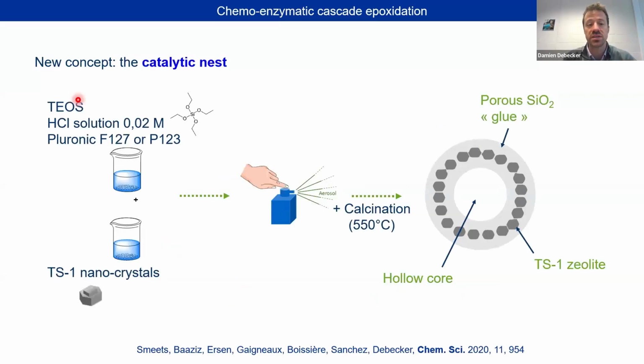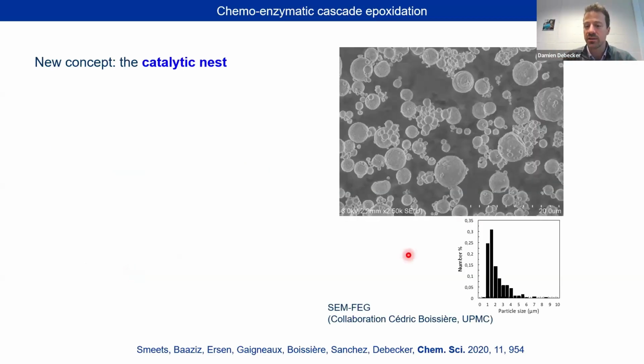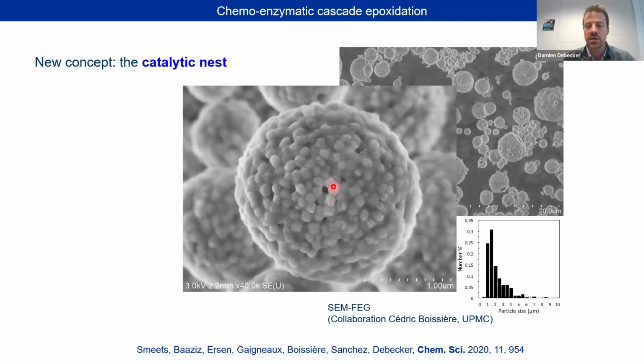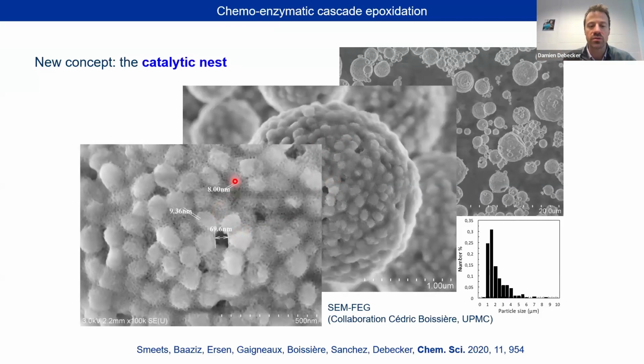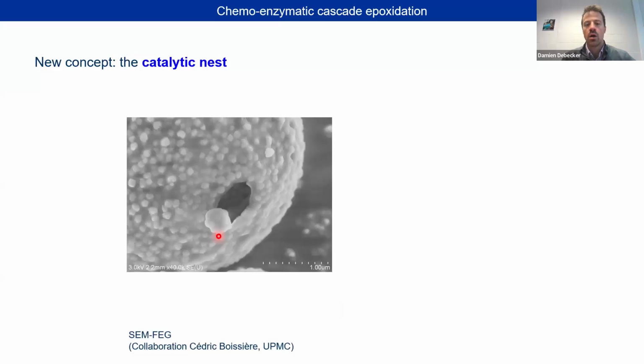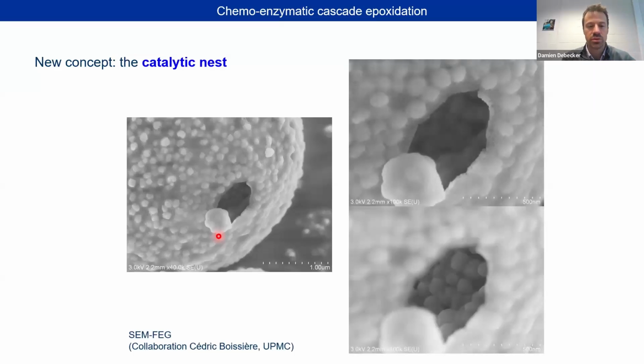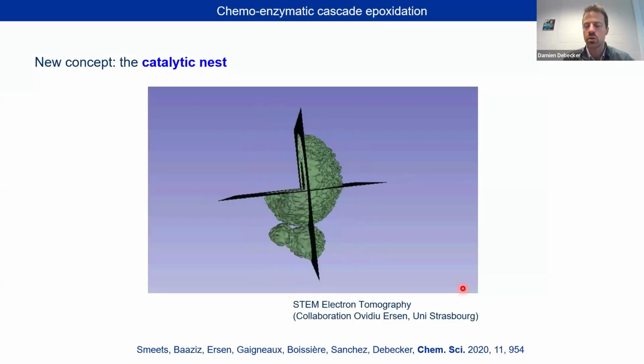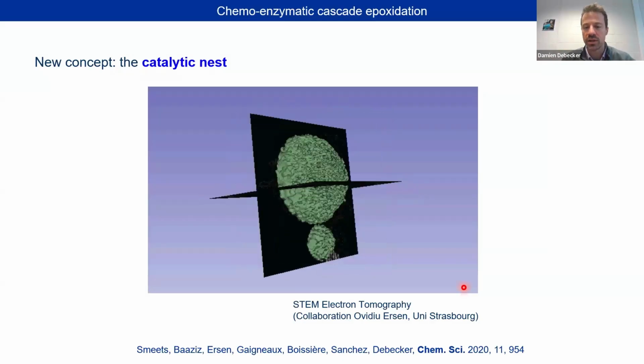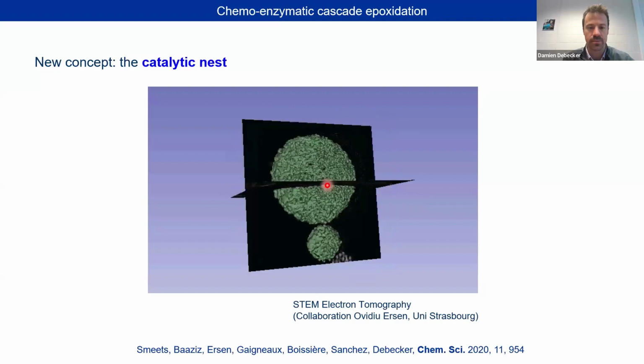So of course, how do we make these catalytic nest particles? By spray again. We spray a suspension of nanocrystals and we shape those spherical particles. They look like these spheres, about 1 or 2 microns here. You can zoom in, you see the zeolite nanocrystals here, and the binder that we have used, a porous silica. If you zoom in a little bit more, you see the pores of about 8 nanometers here, and interparticle pores as well. Some additional images just for the beauty of it, where you see the zeolite crystals, and also 3D tomography to show you that we indeed have hollow particles.